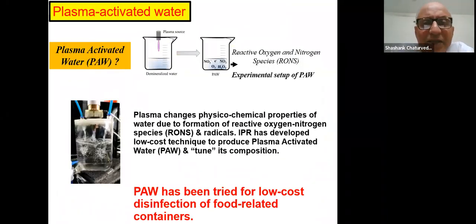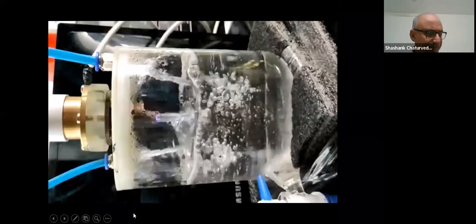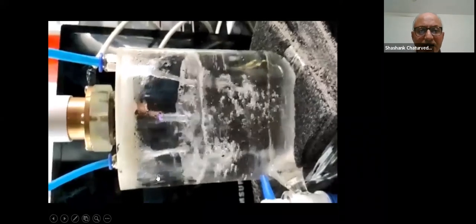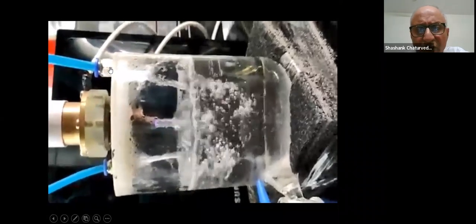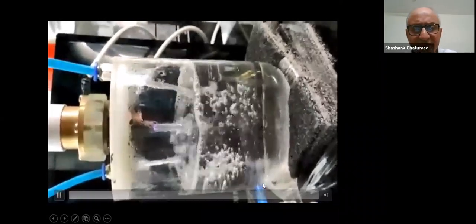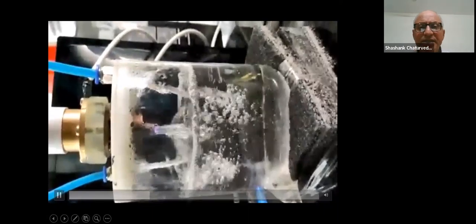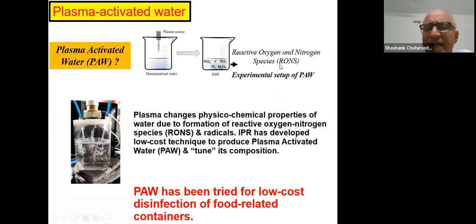We also developed something called plasma activated water. Well, what is it? Let me just show you a video. It's a plasma jet that I talked about, which is made to interact with water in a beaker or something. What's the great thing about it? You get a lot of reactive oxygen and nitrogen species forming inside the water. And these typically last for a few hours to a few days. We made it at a very low cost, and we can tune the composition. We can modify the plasma so that you get different species composition.